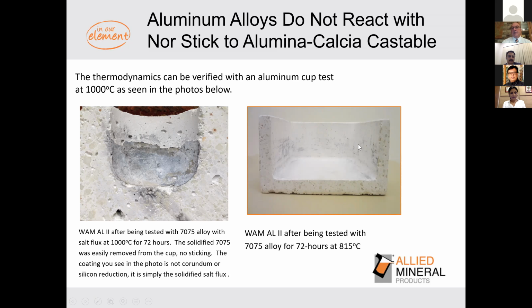And again, here you can see the peelability. This had aluminum up to this level, and we were able to pull the skin of aluminum out of the refractory without any coatings. Because again, the industry has historically used coatings to have a parting plane, but this, with no coating, peeled perfectly.